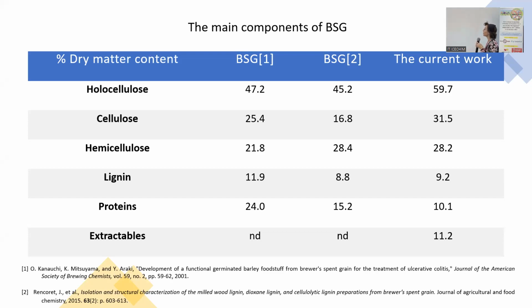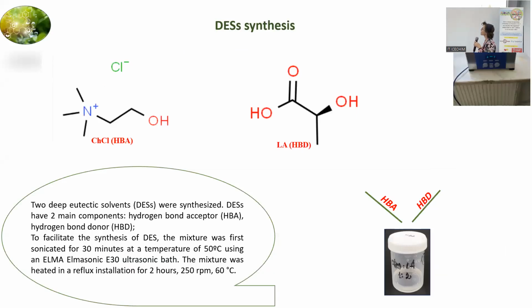The main components of BSG are cellulose, hemicellulose, and lignin. We obtained a percent of 90.2 in our work. The synthesis of this DES is simple, feasible. The melting point reached only 60 degrees compared to the main precursors, and it is known that a deep eutectic solvent is composed of two main components: hydrogen bond acceptor and hydrogen bond donor. In our case, choline chloride is a hydrogen bond acceptor, and lactic acid is a hydrogen bond donor.